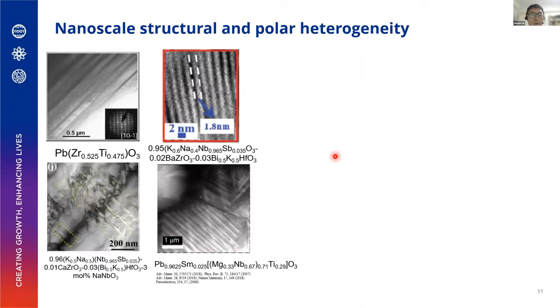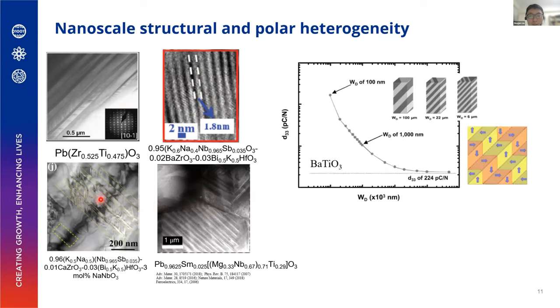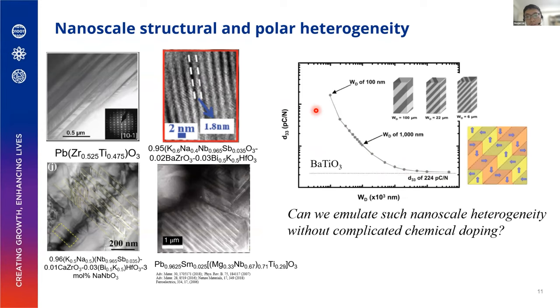Another common phenomenon in these high piezoelectric coefficient materials is that you have very fine nanostructural heterogeneity and also some polar domains. There are simulations showing that if you have finer domains, you can have a higher piezoelectric response. So we are thinking, can we emulate this kind of behavior without using complicated chemical doping?